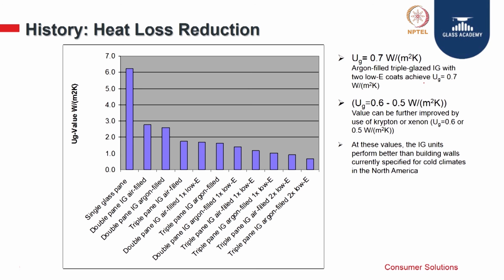This is just to give you a brief on how the U value changes with different composition in a DGU. The single glass pane will give you the highest U value, it will be more conductive. So, the function of having a DGU is to reduce the thermal conductivity. The U value gets reduced, but you have a solar heat gain which also has to be taken care of by using a proper coating on the glass. Just by doing a double glass, this gets reduced by half. So, you get less conductivity.